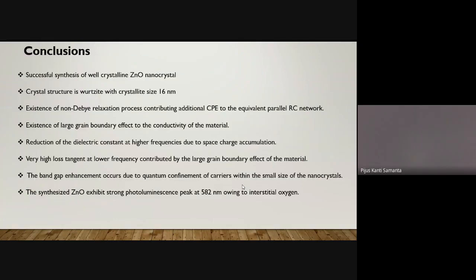So in conclusion, we have successfully synthesized well crystalline zinc oxide nanostructures of wurtzite crystal with size 16 nanometer. It exhibits a non-Debye type relaxation process which induces an additional phase in the equivalent RC network of the dielectric model. We observe a large grain boundary effect, since the material is nano-sized, so lots of grains are created. So grain boundary effect is quite high as expected, and loss tangent increases in the low frequency region due to space charge accumulation. And I have already mentioned that this optical emission is due to the oxygen interstitial.